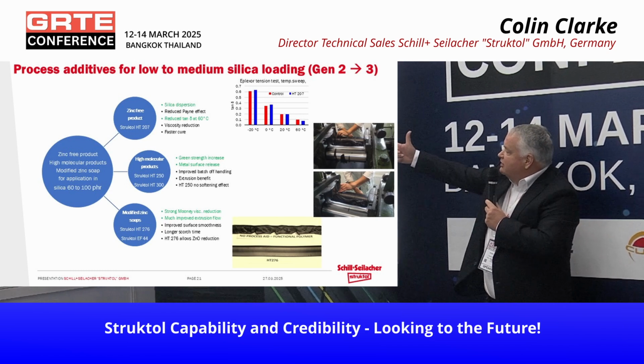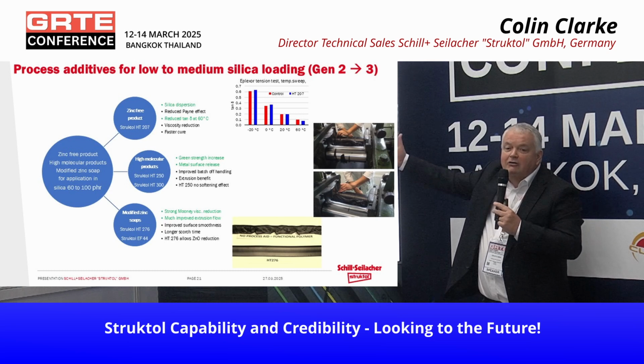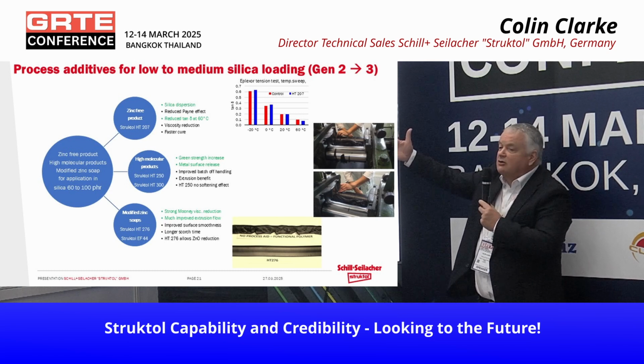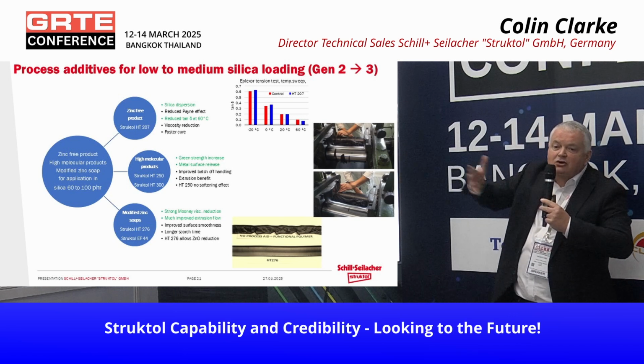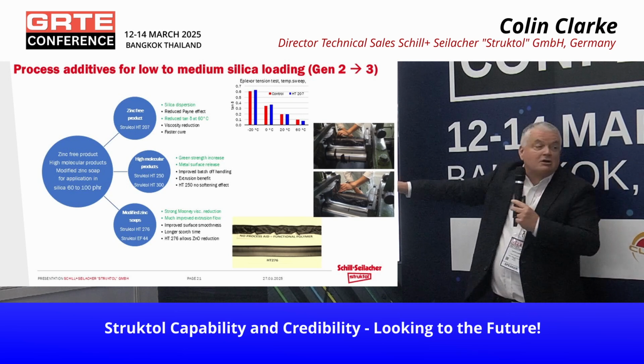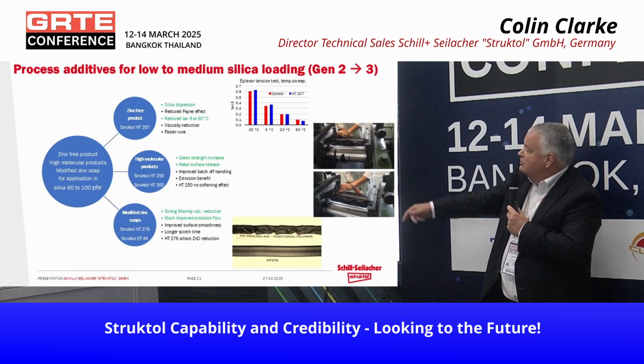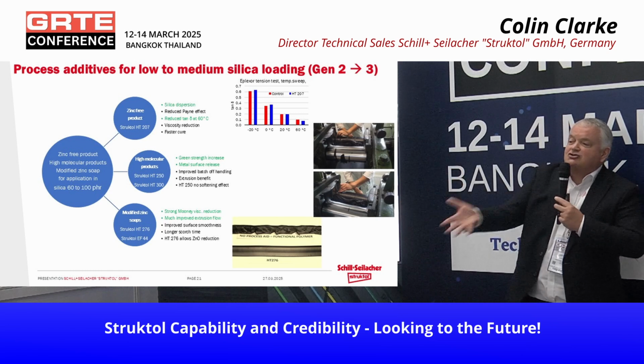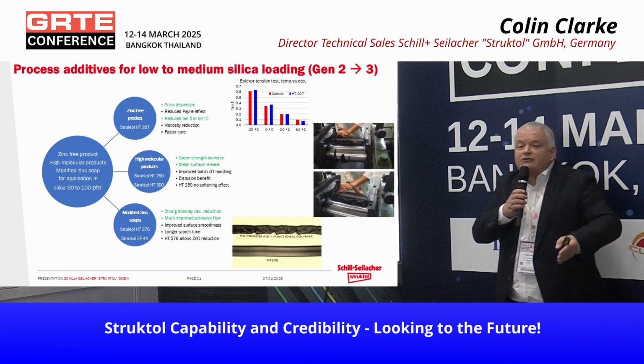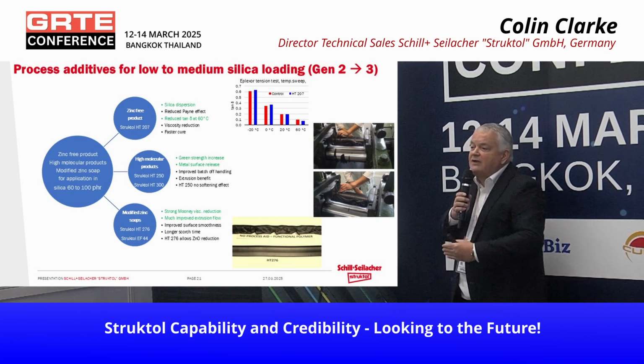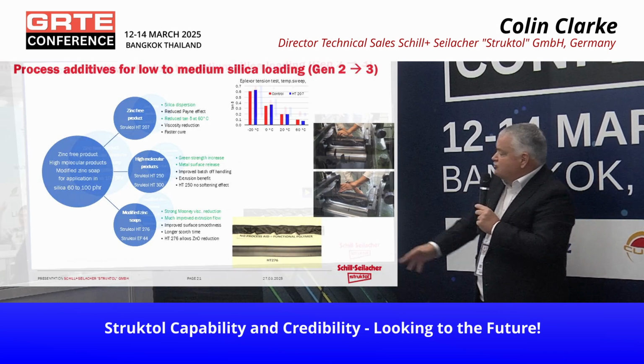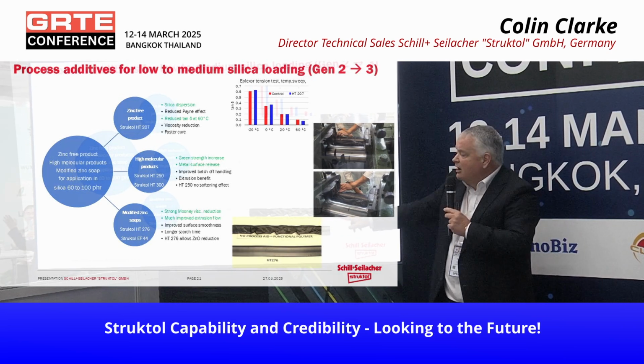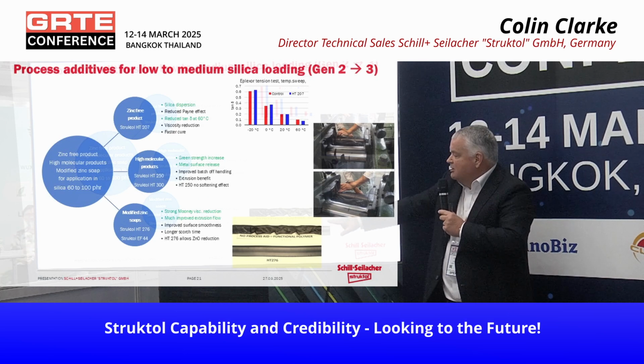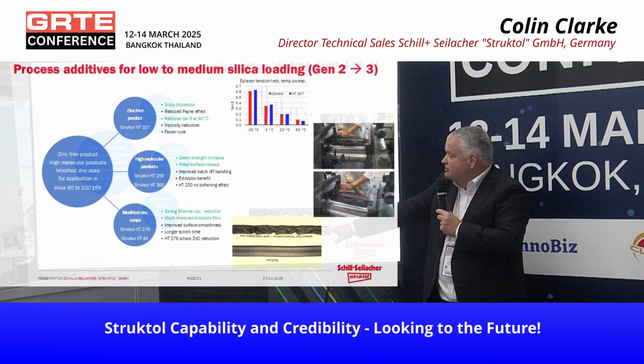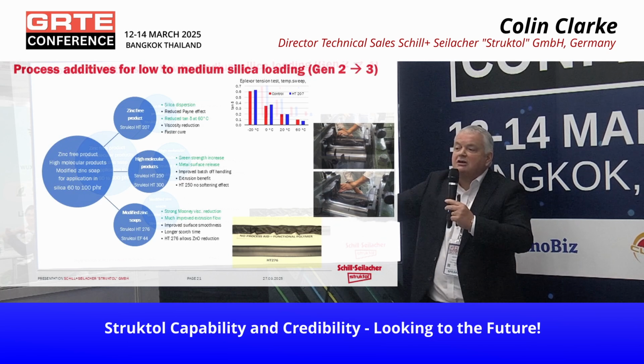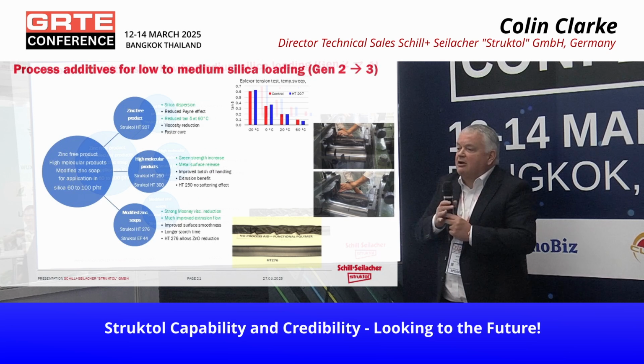So this is a modern tread compound. It becomes very sticky, very high loading of silica, high loading of resin, really difficult for the operators to handle. So it's really difficult to get good release for that type of compound. With the process additive in place, the same compound, the operator can take the material away very easily. So this is an example of the really targeted release and much improved handling of a modern tread compound. Of course, these compounds are very difficult to extrude. The high loading of silica gives us a very rough extrusion. By applying a low loading of suitable process additive, we can really smooth out the extrusion and make the tread really much more regular and uniform, if you like.